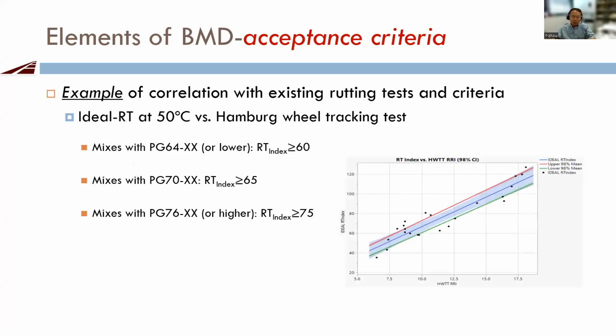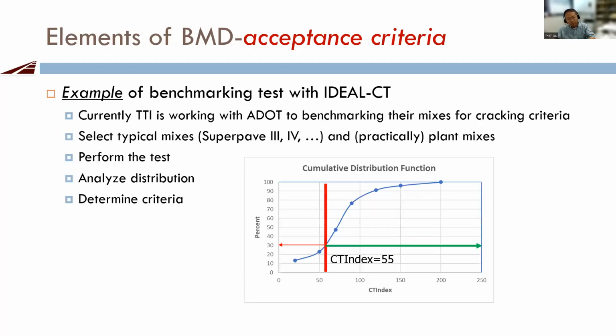I'm presenting 3 practical ways to establish the criteria. Here, this is how we recommend ideal RT test criteria based on the correlation with the Hamburg wheel tracking test. The y-axis is the RT index, the x-axis is the Hamburg wheel tracking data. Based on this correlation, for 64-22 or 64-28 binders, the minimum RT index is 60. For PG76, the minimum is 75, PG70 in the middle here.